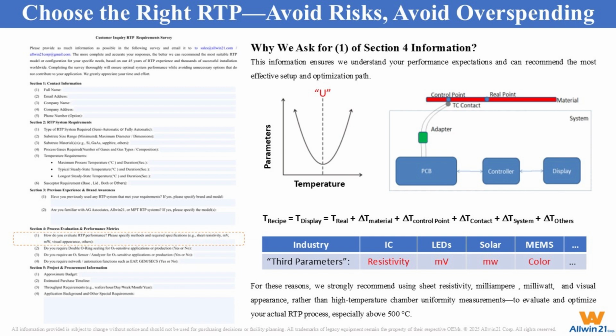It is important to note that RTP heating is inherently non-equilibrium. Traditional thermocouples or TC wafers cannot accurately reflect the true thermal gradient of the actual substrate, especially above 500 degrees Celsius, where thermocouple contact and environmental effects create large measurement errors. As the industry often says, you never know the exact temperature of your real substrate. What matters is whether the process results are uniform, repeatable, and meet your specifications.